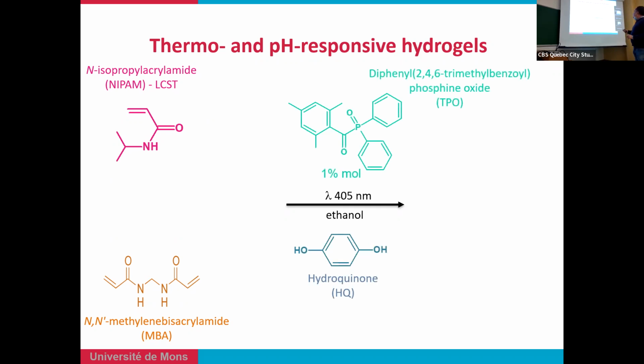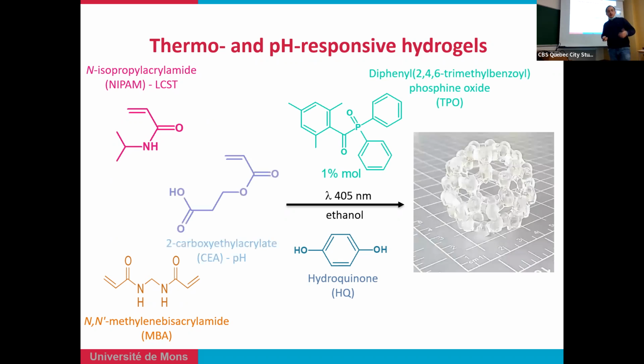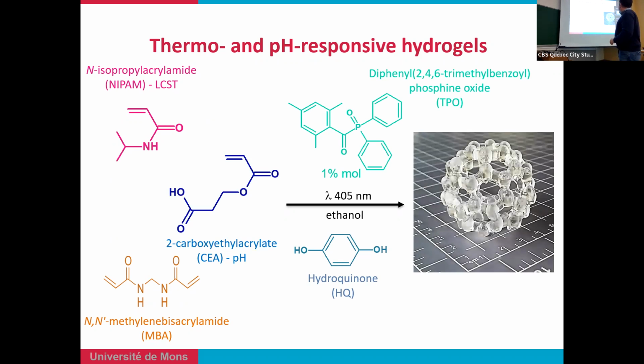Therefore, you need to use a photoinitiator that is active enough, and also a quencher to help the resolution. In fact, if you don't add any quencher, you can have a certain concentration of radicals that can push through the photopolymerization and create some defects at the end. So you need a quencher to stop the reaction when you stop the light, in order to get a well-defined object.